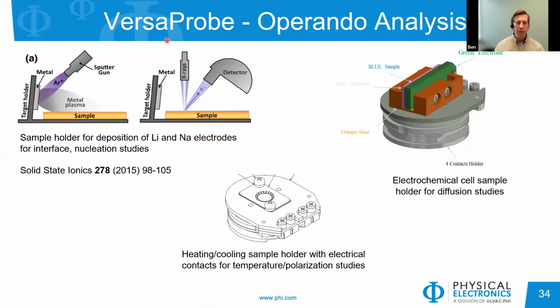One option that we have is a special sample holder where you can actually sputter an anode type material onto your sample. And so you can monitor the evolution of species as you sputter that material onto the sample. We have an electrochemical cell where your sample would mount in a cross section, and you can bias one side versus the next and look at any evolution of species across the cross section.